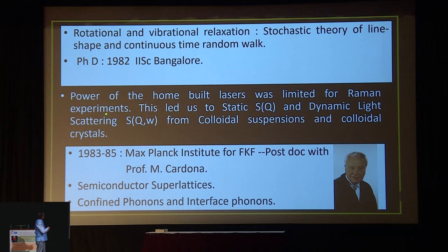But soon we realized, after this was in 1982, that the laser power, which was only 20 to 30 milliwatt, was not enough for Raman scattering. We needed much more power and we were limited. Just that constraint that we could not import any argon ion laser, that was prohibited.